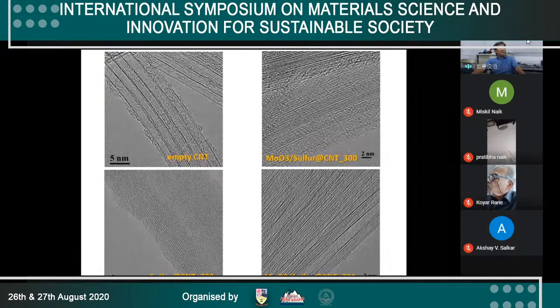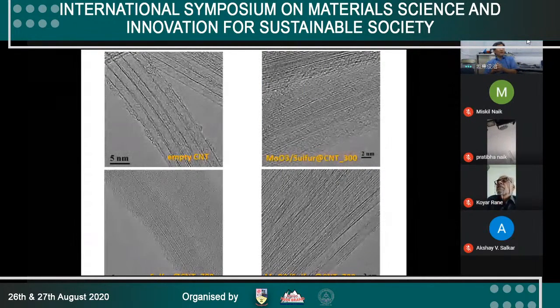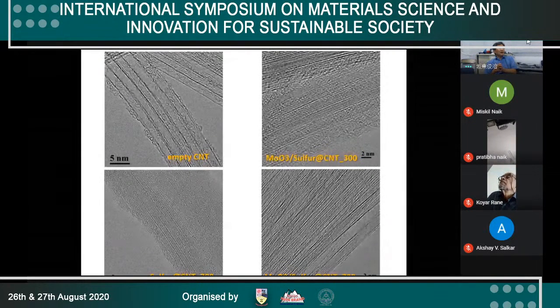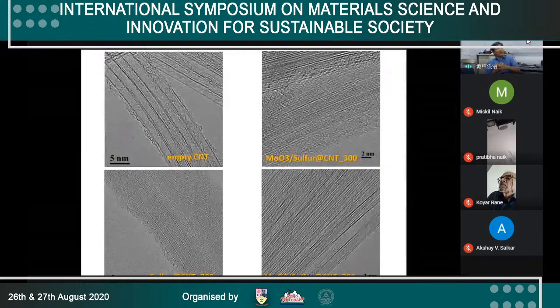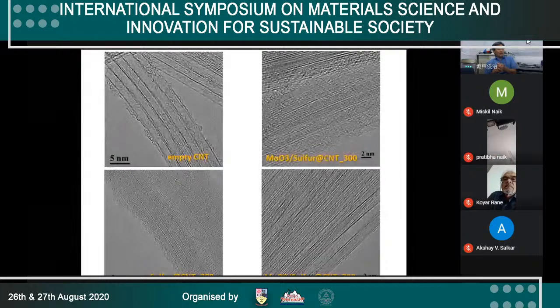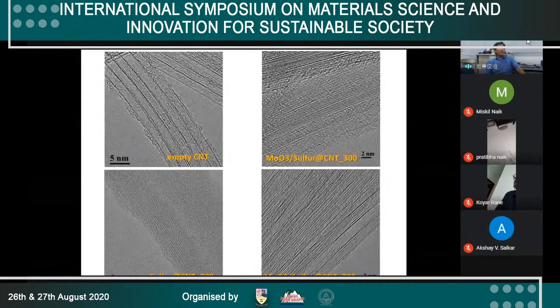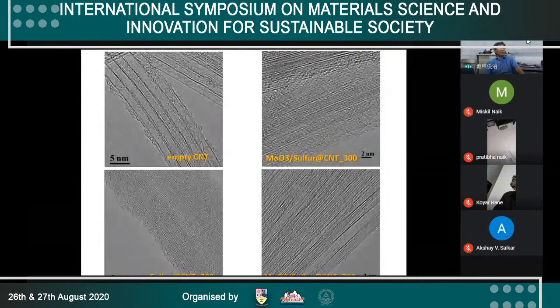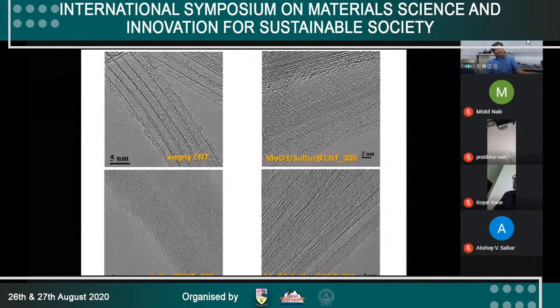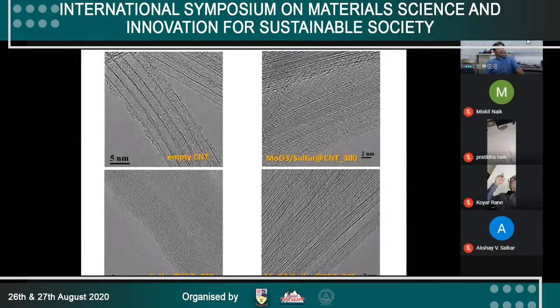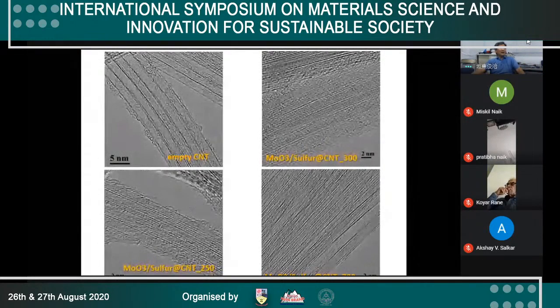Next slide, please. Okay, this is a transmission electron micrograph of the nanotubes. The empty nanotubes is meaning the nothing inside the nanotube. When we synthesize the sample at the 300 centigrade, you can see some atomic image, the lattice image inside the nanotubes. And it's different from on the sulfur. The next click. Okay, this I skip to the next.